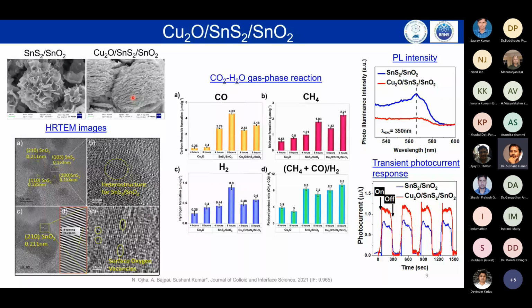Now, when we looked deep into the HRTEM, what we have seen is that this has formed a heterostructure. That was our goal, to form a heterostructure using SnS2 and SnO2, and we achieved that using the hydrothermal reactor. And when we looked into the structure, we saw that there were surface oxygen vacancies, which you can see here.